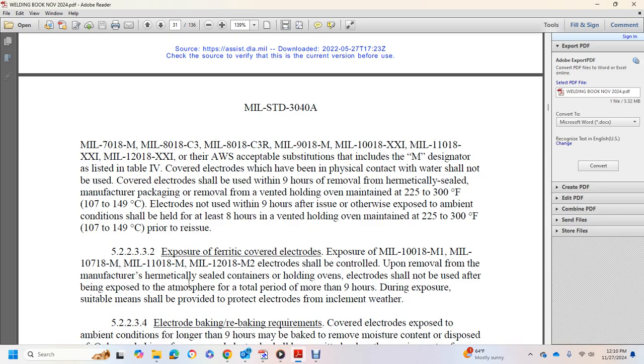Exposure of ferritic covered electrodes, with exposure to MIL-10018-M1, MIL-10718-M1, MIL-11018-M1, MIL-12018-M2 electrodes, should be controlled from the time of removal from the manufacturer's hermetically sealed containers or holding ovens. The electrode should not be used after being exposed to the atmosphere for a total period of more than 9 hours.